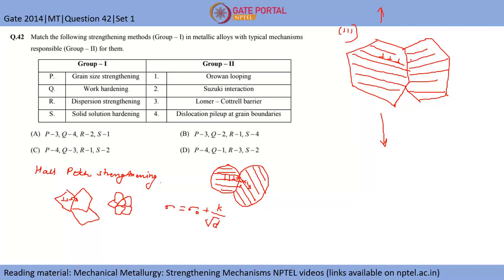Hence this increase in stress which is required for the dislocation to go into another grain and start plasticity in this complete grain is basically the grain size strengthening. Hence if you have more number of grain boundaries, you will have more dislocation pileups at grain boundaries, which will lead to more strengthening.